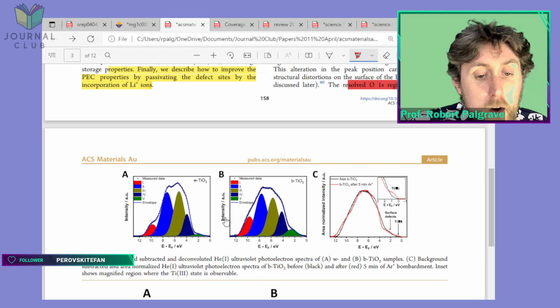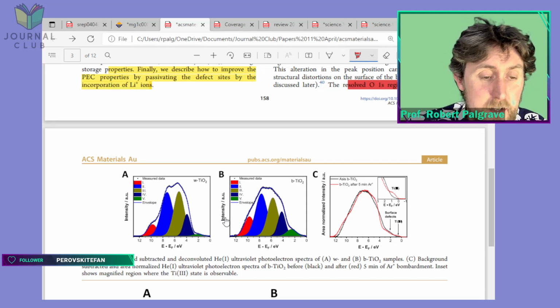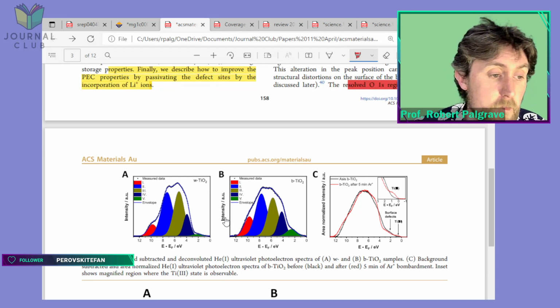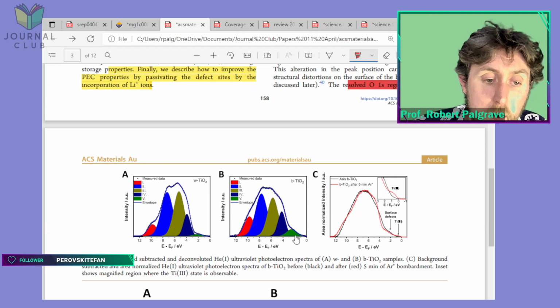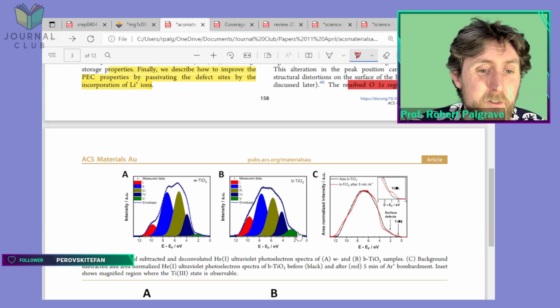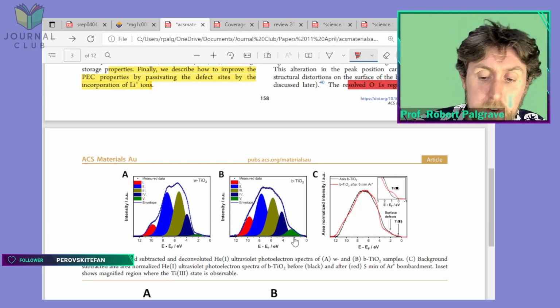So, what do surface defect states mean? Certainly at the moment it's not very well defined what they actually mean by surface defect states. But on the face of it, it does look like there is a greater spectral intensity here in the black TiO2 compared to white TiO2. That's one of the differences you would say between it.